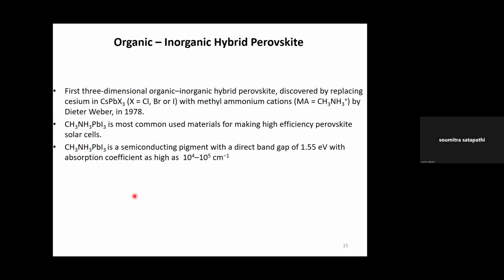The first three-dimensional halide perovskite reported in the literature was CsPbX3. Here you see this is another perovskite crystal structure, and it satisfies ABX3, where B is lead, X can be chlorine, bromine, iodine, and A is cesium, the cation. But you can replace cesium with any of the organic cations, for example, methyl ammonium, CH3NH3 plus. Then you call it CH3NH3 lead iodide. This is the typical perovskite, which has a direct band gap of 1.55 electron volt, and has been widely utilized for making solar cell photovoltaic devices in the industry also.